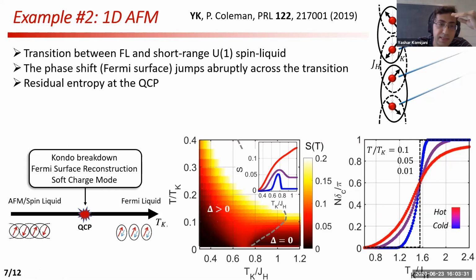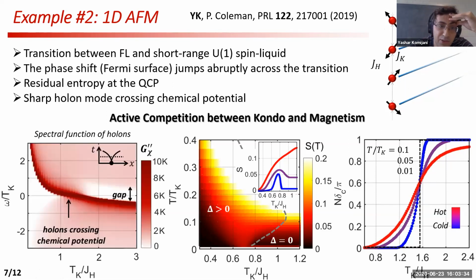And this naive thought turns out to be actually correct, because this is the spectral function of the holons as a function of frequency and the tuning parameter. They are very incoherent, but most of the weight is concentrated on this mode, which comes down and crosses zero frequency, or chemical potential, here and goes down. And remember that this is a fermionic mode. So when the holons are occupied, we have a large Fermi surface, and when they are empty, we have a small Fermi surface. And at the critical point, the holons are critical.